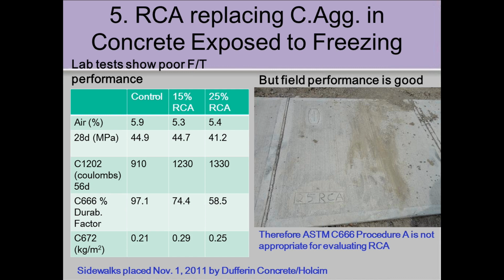The air contents were about right. The strengths were close on these at 28 days. There was an increase in the permeability values with the increased RCA, but they're still less than the 1,500 we would require. The durability factor, what's interesting is that this C666 freeze-thaw test, you can see the performance dropping off way quickly.